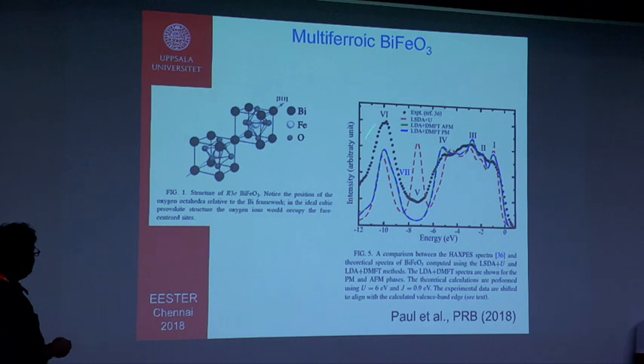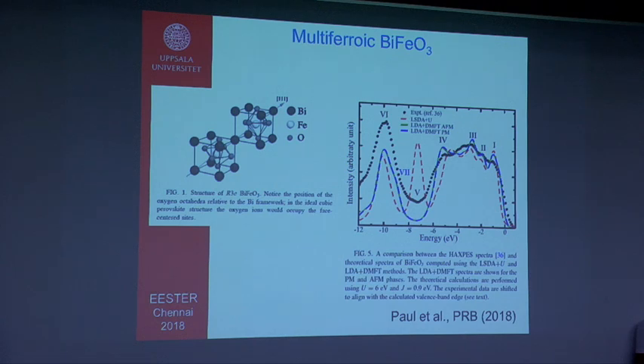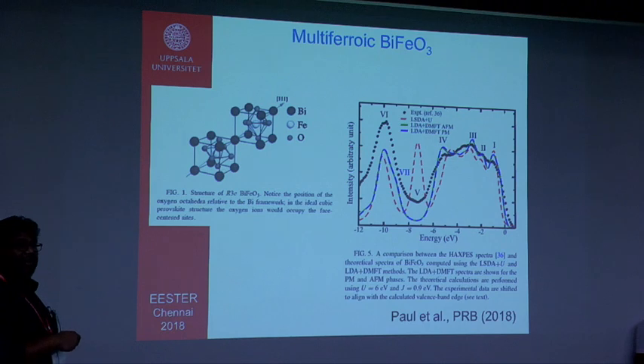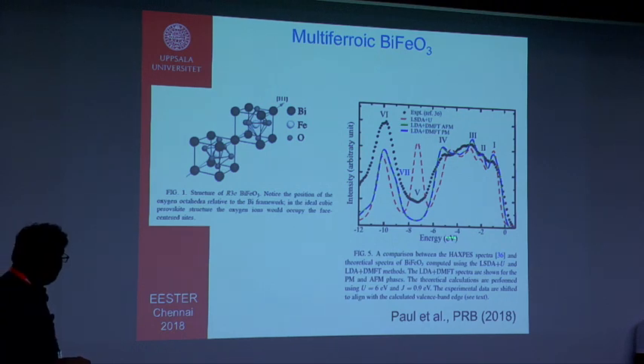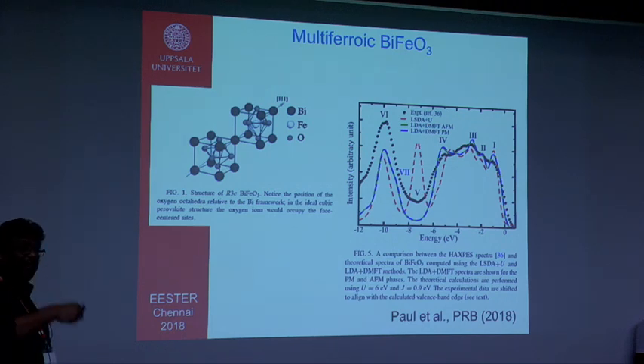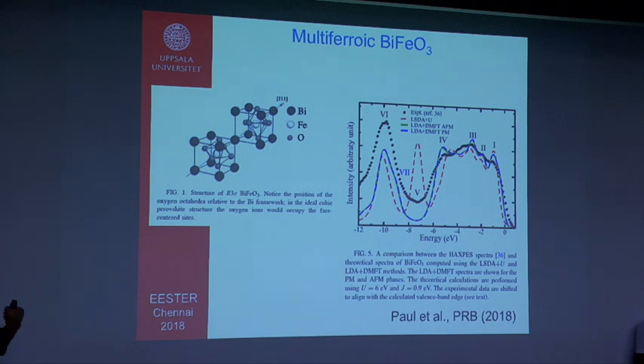What we show here is the comparison between the experimental spectra and different spectra generated by different theoretical methods. So these black ones are the experimental HAXPES spectra Professor Maiti was talking about. This is a high energy photoemission experiment, so you really bombard with high photon energy, something like 6 keV, 8 keV. So this is a very reliable result.